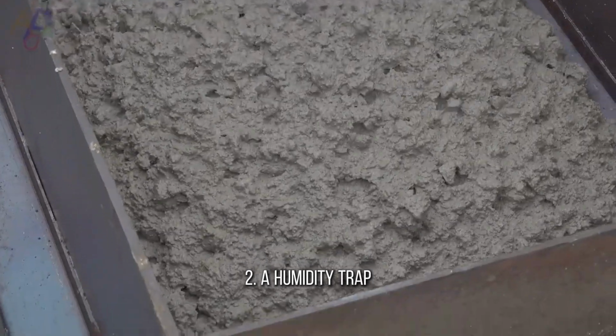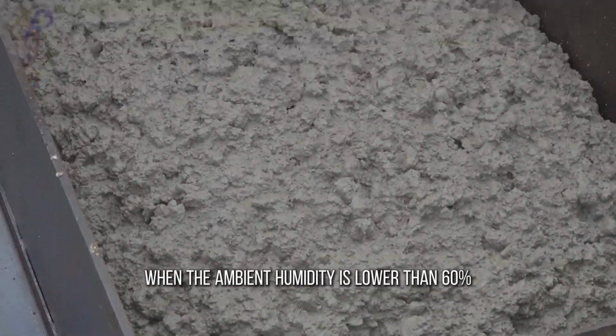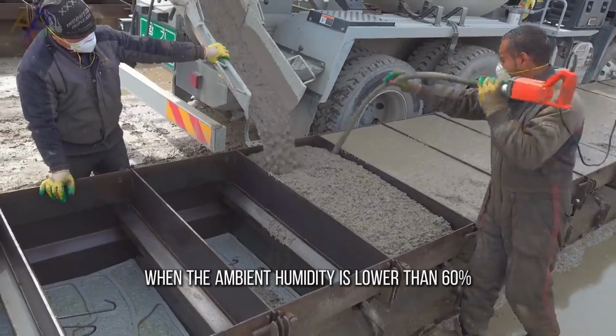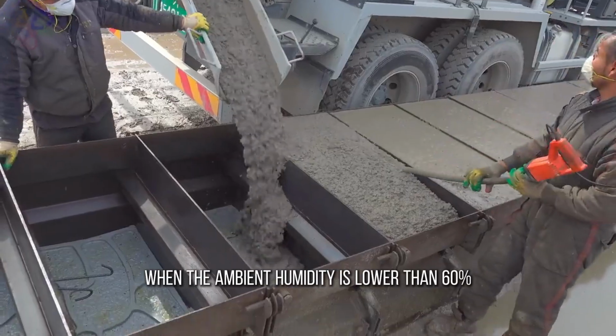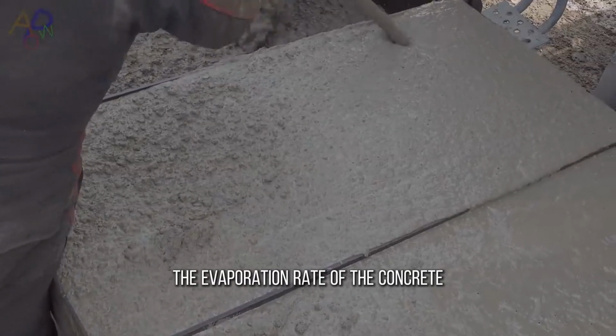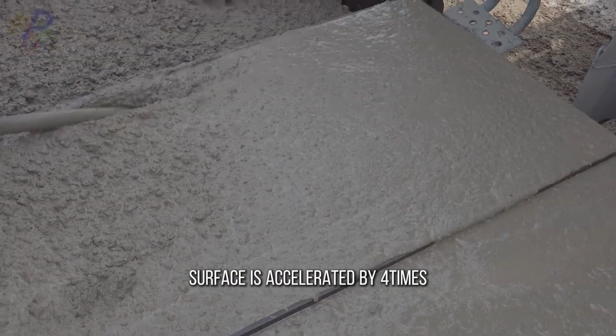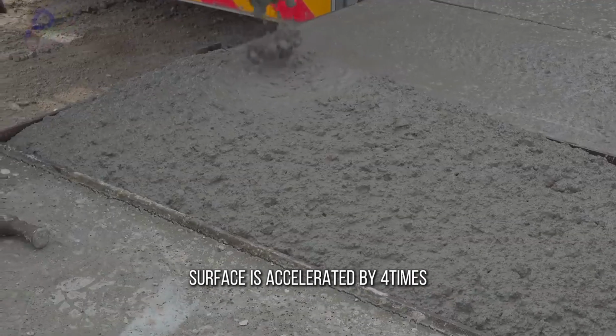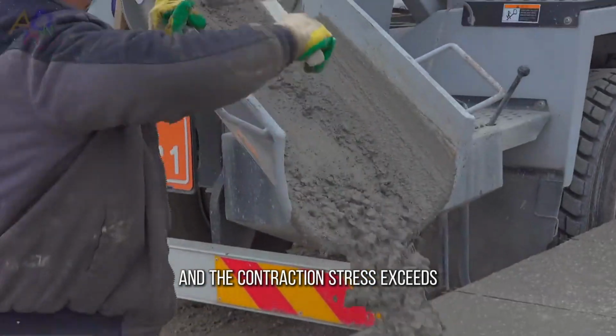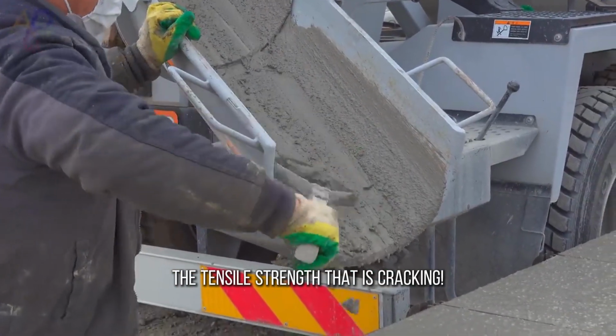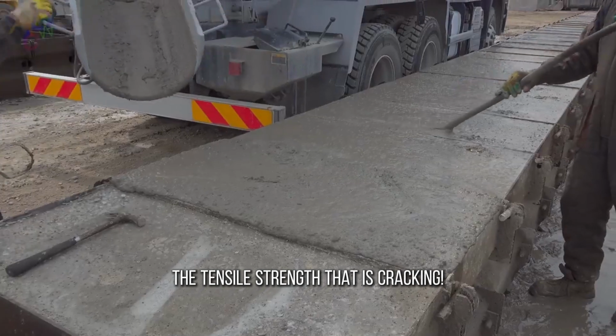Two, a humidity trap. When the ambient humidity is lower than 60%, the evaporation rate of the concrete surface is accelerated by 4 times, and the contraction stress exceeds the tensile strength, that is, cracking.